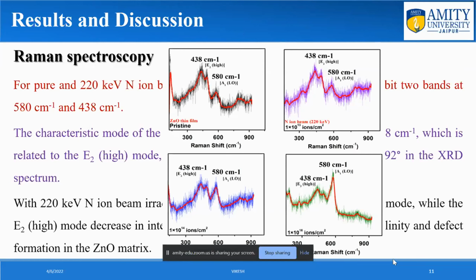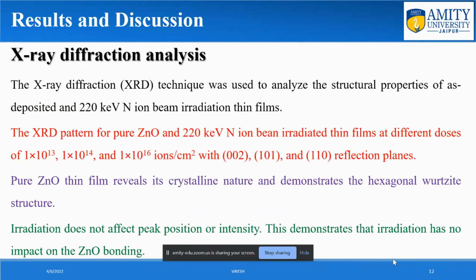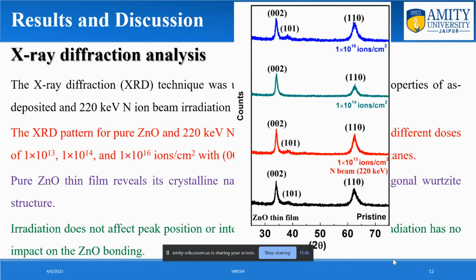And now XRD diffraction analysis. The XRD diffraction analysis technique was used to analyze the structural properties of as deposited and 220 keV ion beam irradiated thin films. The XRD pattern for pure ZnO and 220 keV ion beam irradiated thin film at different doses like 1E13, 1E14, 1E16 ions per centimeter square with different reflection planes.